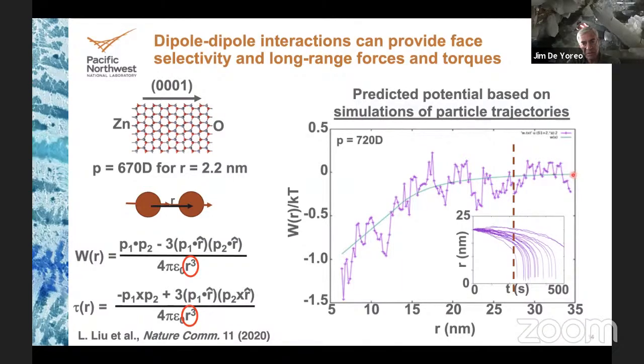So the result of the simulation is the blue curve. It's the potential versus separation. These are the individual particle trajectories in the simulation. The purple is the data that I showed you earlier. He adjusted the dipole moment in the simulation so that the data and the model match at far distance. And the dipole moment needed to do that is very similar to what one would calculate based on literature for zinc oxide. And with that dipole moment, then you can see that the simulations closely reproduce the experiments.